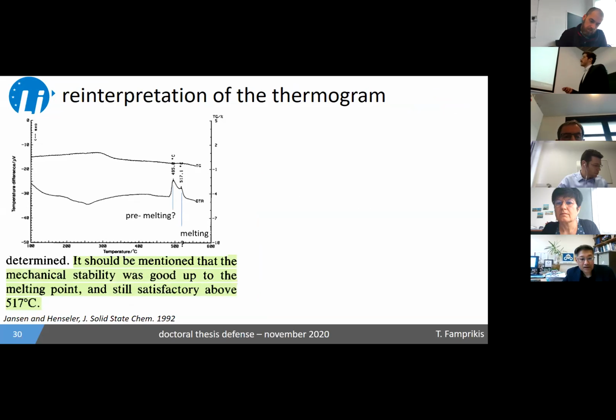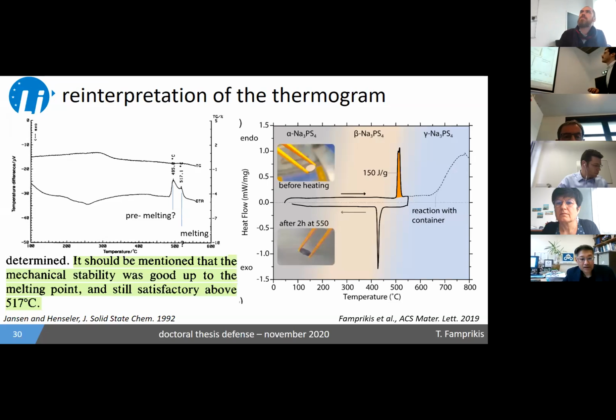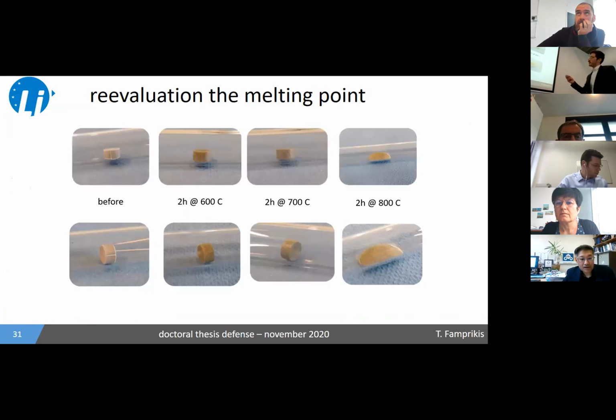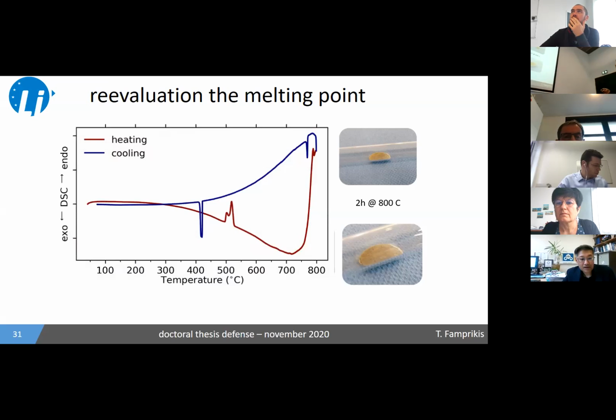So just to go back and set things straight, this is the same thermogram that I showed in the beginning. Indeed, the mechanical stability of the sample is fine after 500 C. I concur with that. And this is because it's not a melt. We can reproduce this thermogram, and we can go further to actually determine the true melting point of the material. A simple visual test shown here shows that I'm still solid if I heat up to 700 C, and I actually melt, I lose the shape of my initial object, only if I heat up to 800 C. And through more DSC experiments, we can determine the start of the melting at around 760 C.